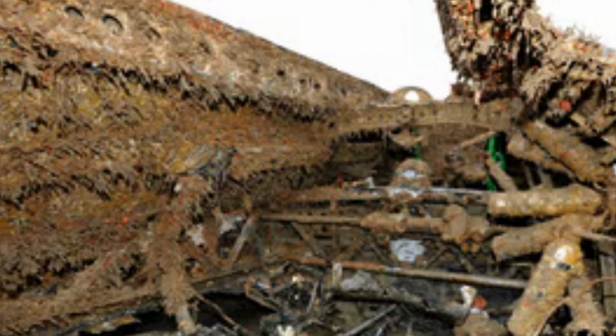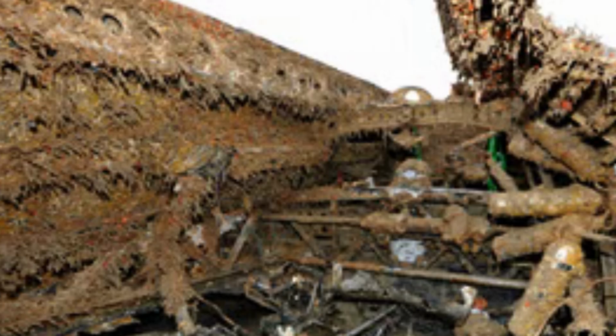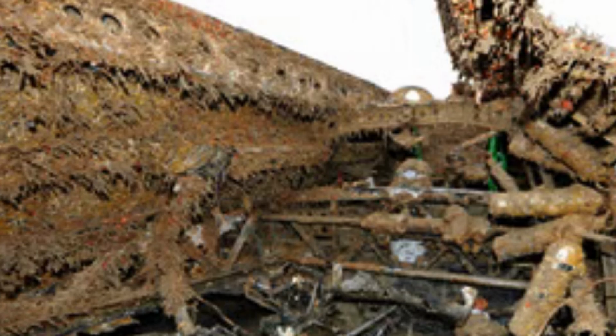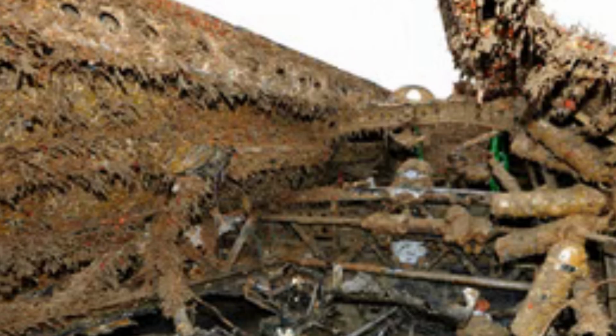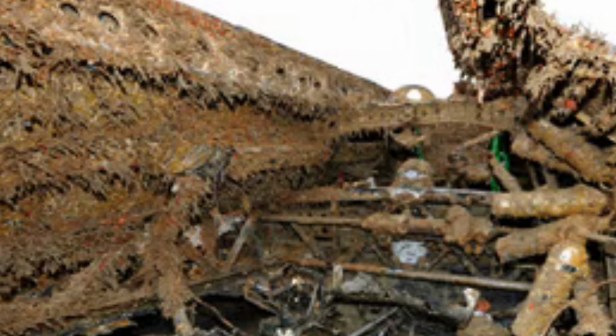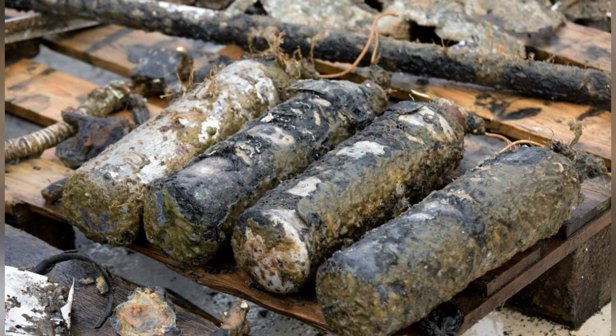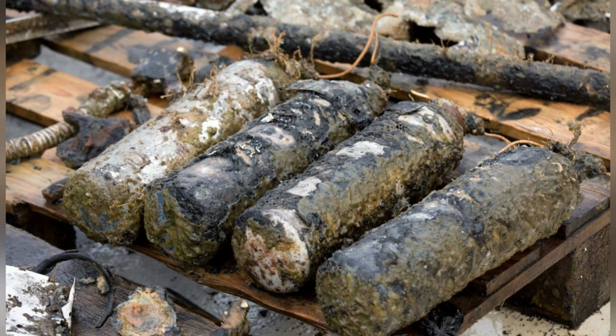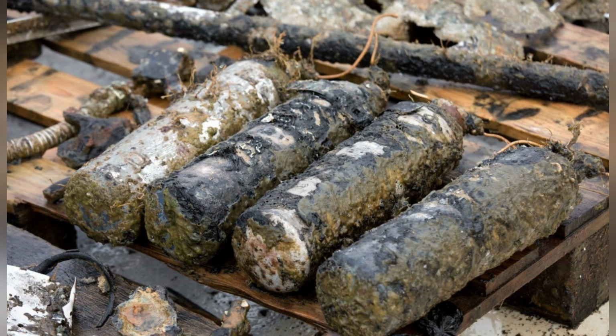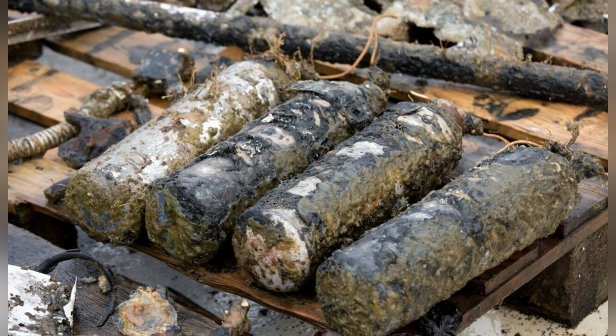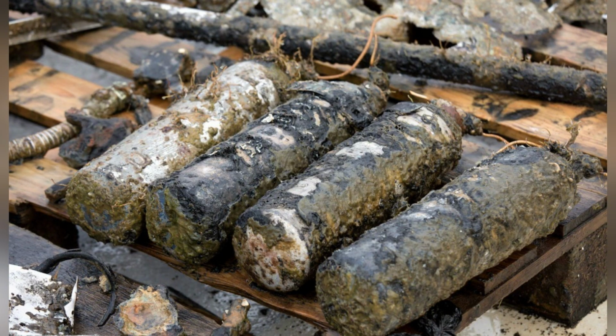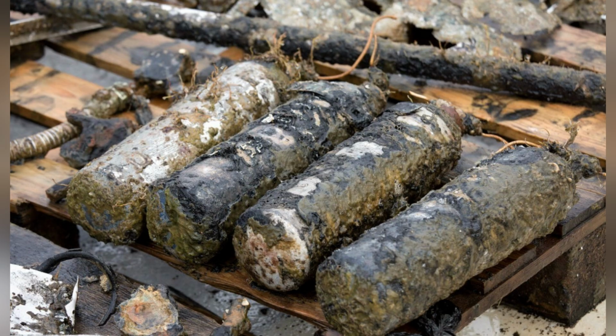It marked the beginning of a chemical siege. The moment the airframe broke the surface of the English Channel, the protective equilibrium of the underwater environment was shattered. The aircraft was now exposed to an oxygen-rich atmosphere, the catalyst required to activate the chloride salts embedded deep within the aluminum alloy. If the metal were allowed to dry, these salts would crystallize and expand, shattering the remaining molecular bonds of the structure. The exfoliation process would accelerate from a geological time frame to an immediate crisis.